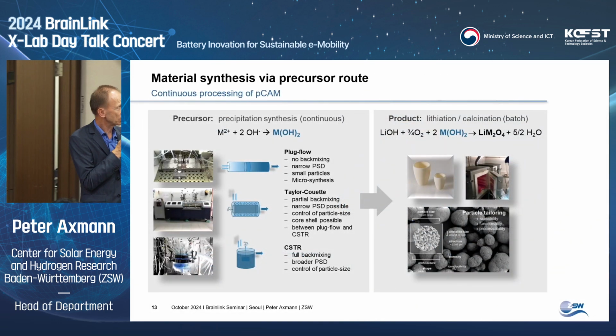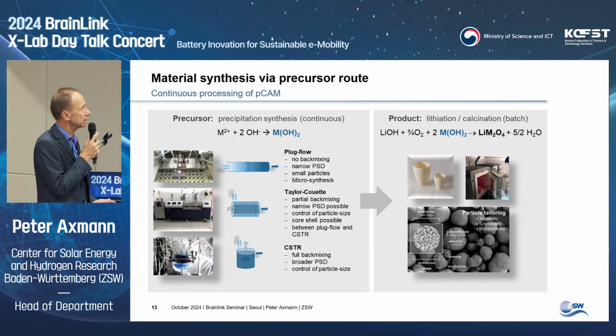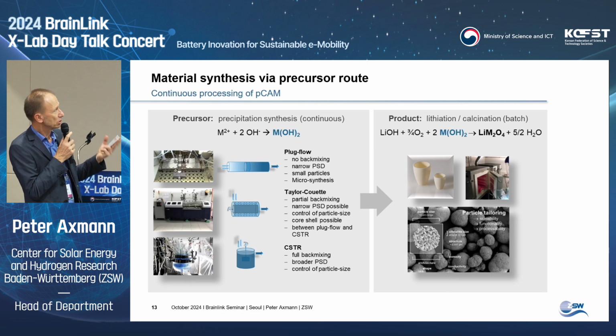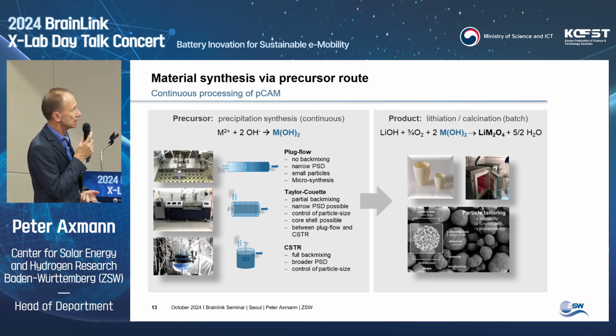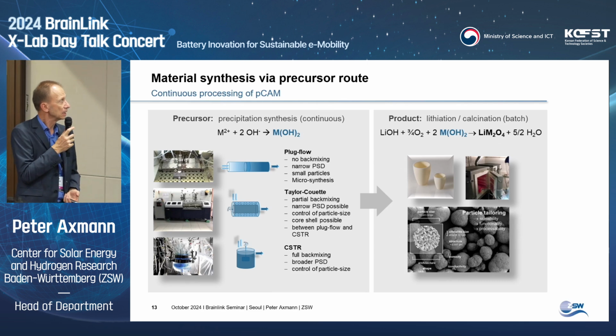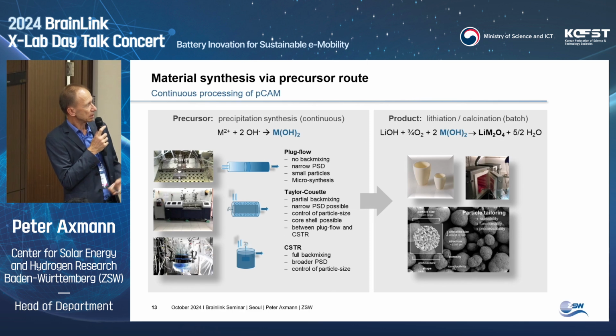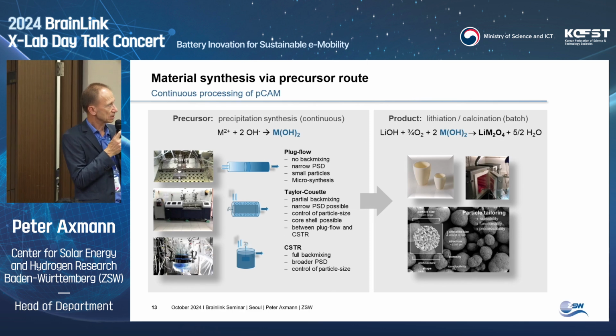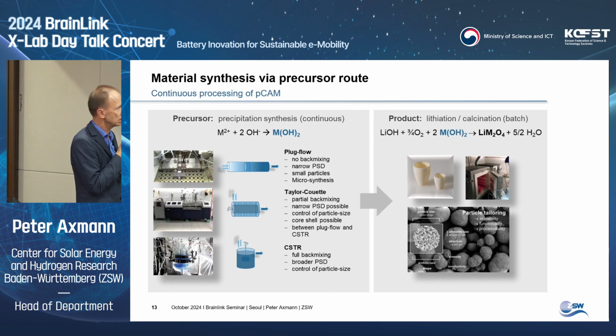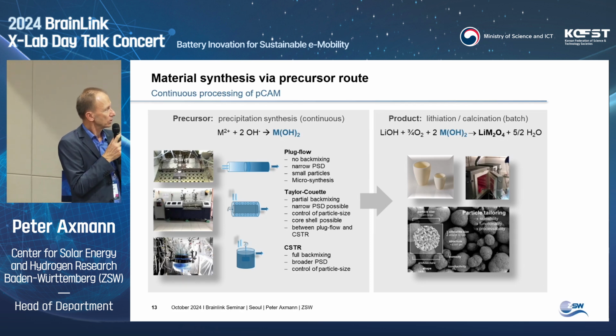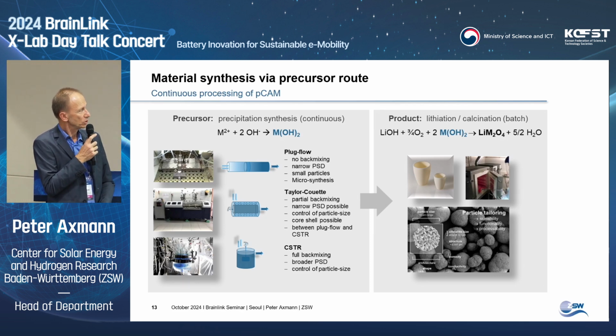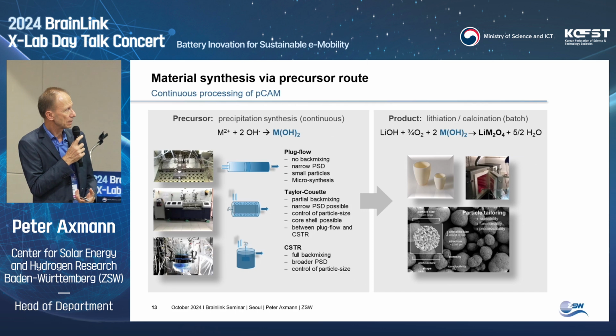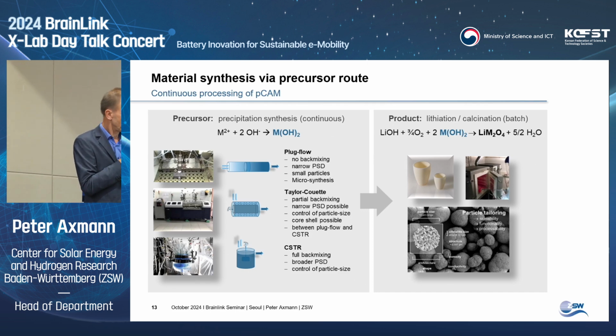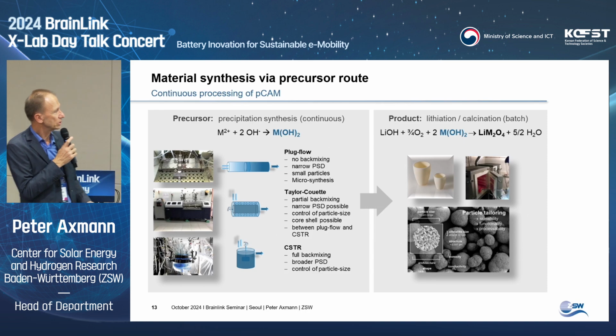Larger coating lines need more than 40 kilograms, just as a pilot line production. And to get this large amount of material in the required quality, you can go via the precursor route to these materials. This is a technically applied route. You make a continuous precipitation of a precursor, the so-called hydroxide, which is still free of any lithium. You have this powder, and in the second step, you add lithium to it, heat it up in the presence of oxygen at high temperatures and end up with a final cathode active material.